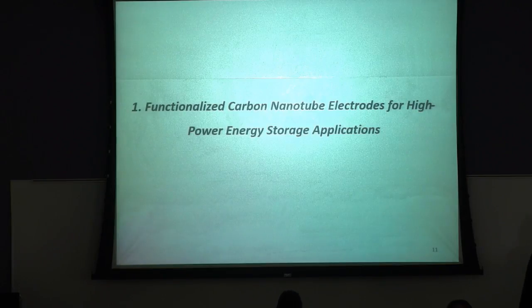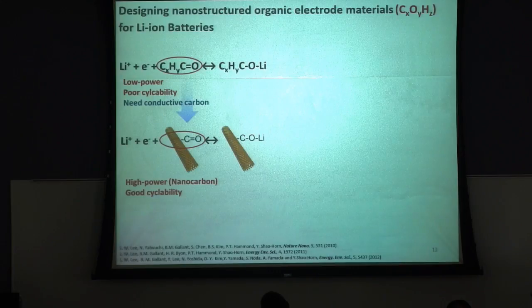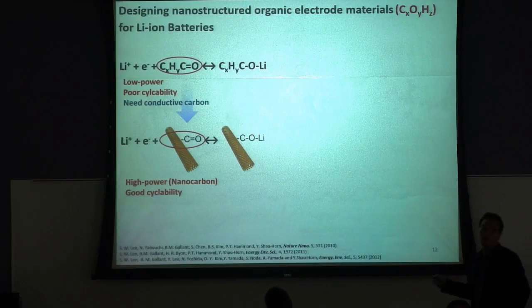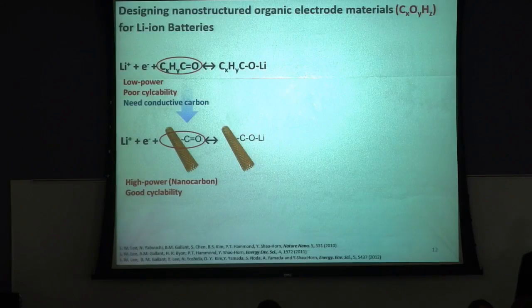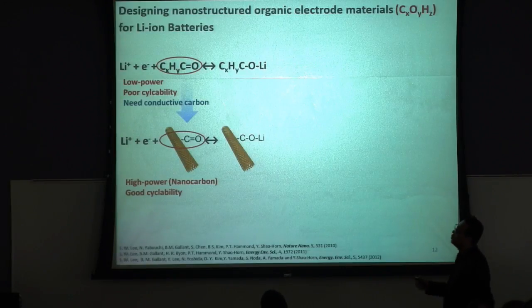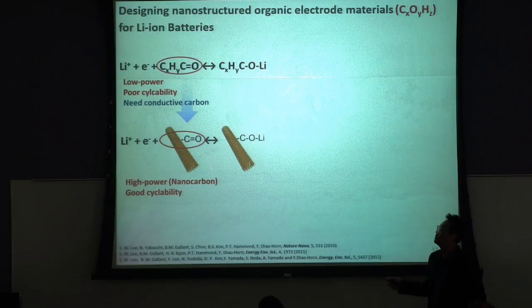The first topic is the functionalized carbon nanotube electrode for high power energy storage application. Let's say these are organic molecules that include carbonyl functional groups. We can expect a redox reaction with lithium ions. But this molecule is insulating, so we have low power, and also poor cycling stability because of dissolution. So we need to mix in a lot of conductive carbon materials to fabricate electrodes.